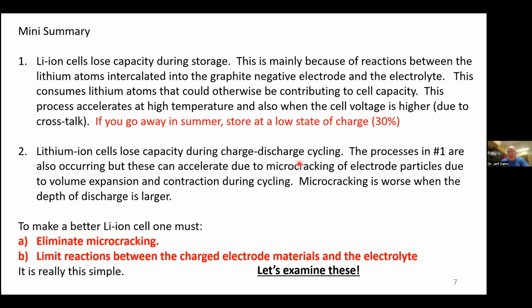Lithium-ion cells lose capacity during charge-discharge cycling. So the processes that occur in number 1 are also occurring, but these can accelerate due to microcracking of electrode particles due to the volume expansion and contraction during cycling. So the particles in the electrodes are expanding and contracting, and that can lead to them cracking and exposing new surface that has to be covered by reaction products. And microcracking gets worse when the depth of discharge is larger. So if you want to make a better lithium-ion cell or one that lasts longer, you need to eliminate microcracking and limit the reactions between the charged electrode materials and the electrolyte. It's really this simple. So let's see how to do that.